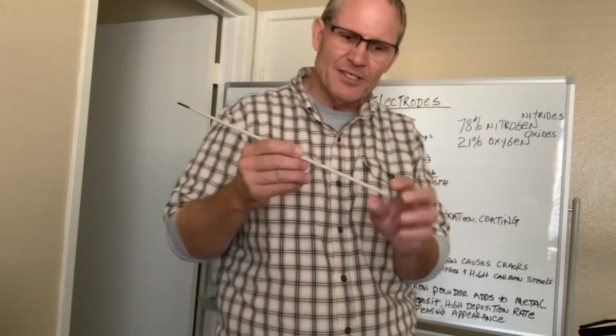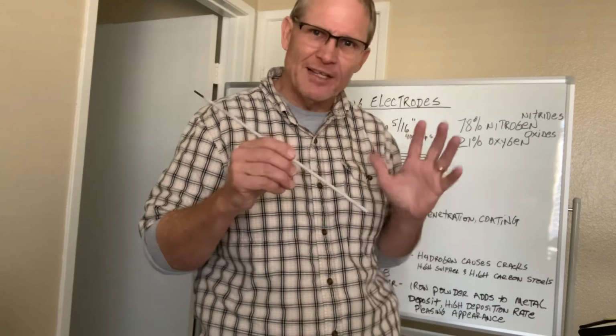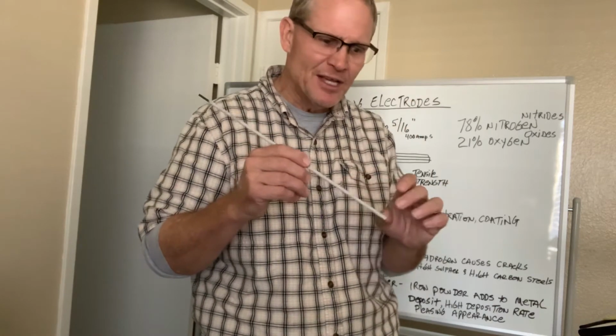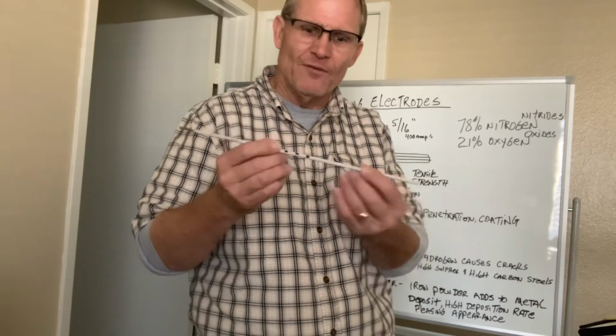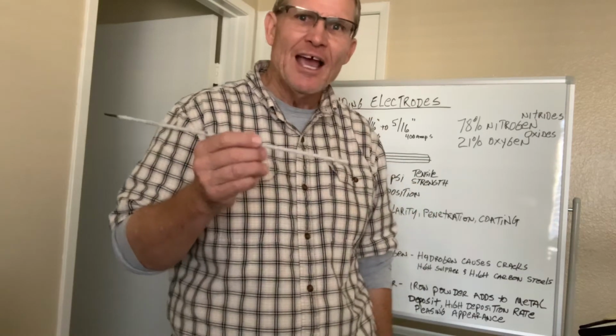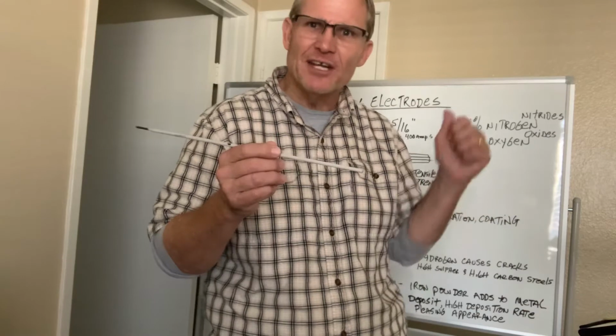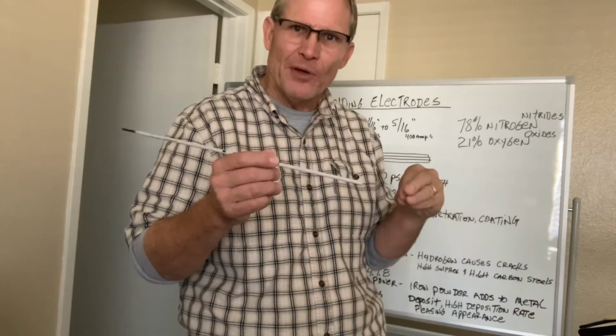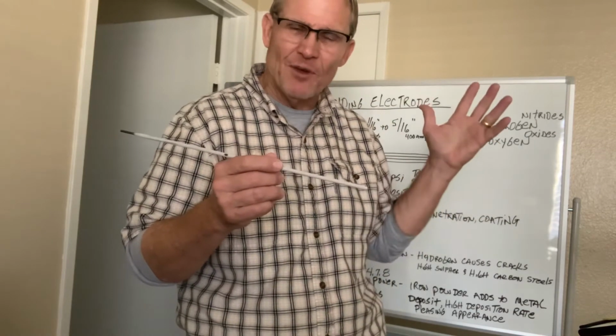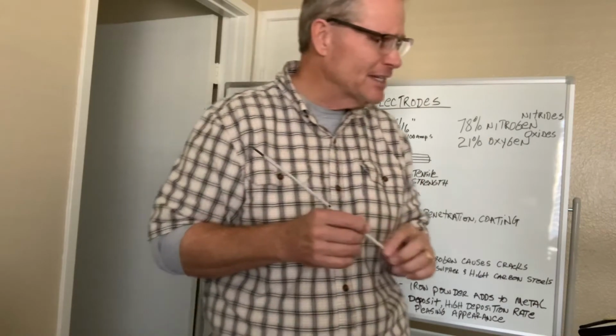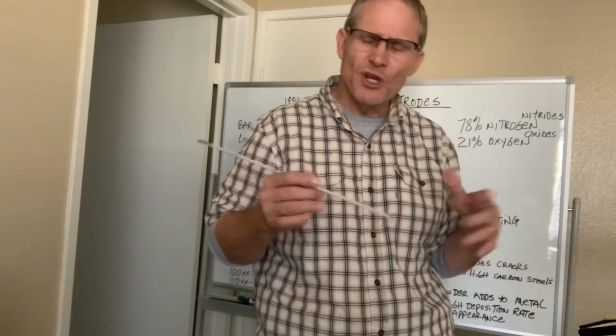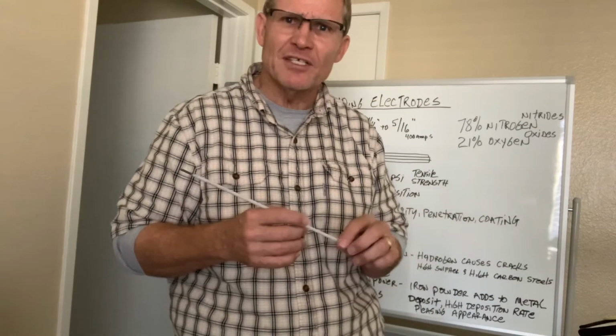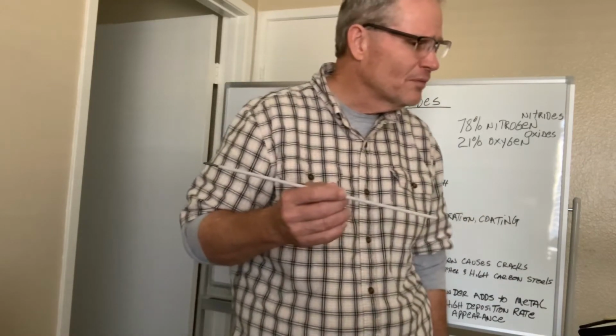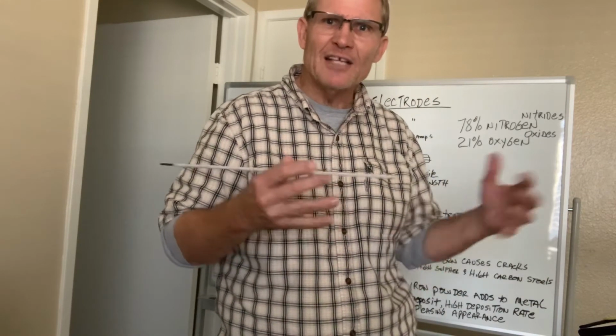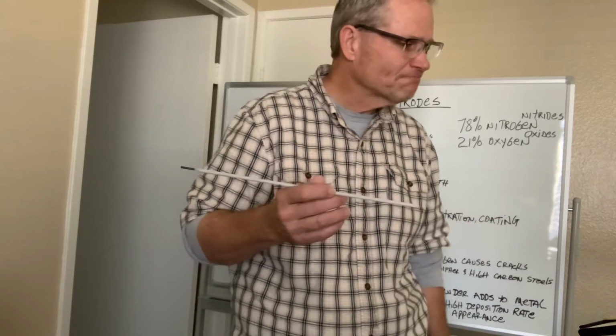The other thing that it does is, not only is it, while it's burning, protecting the atmosphere from the nitrides and the oxides, but the residue that's left over from this flux is called slag. And that slag protects from the nitrides and the oxides while the molten puddle itself is cooling. It protects it from the atmosphere, so you don't get that contamination. It also slows down the cooling process itself, and has the ability to lessen it cooling very quickly.